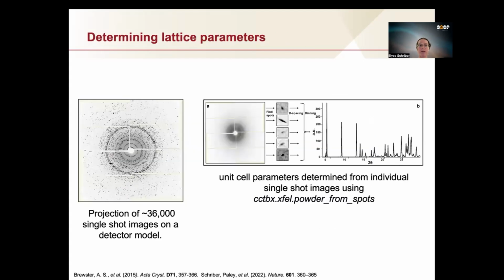So what we developed, using an already made algorithm that was used once previously in 2014 in development of new techniques, is we found that you could determine the lattice parameters from the XFEL experiment. As we said, thousands and thousands of these randomly oriented crystals are sampled, and we get these single shot images. If you take 36,000 of these single shot images and you project them onto a detector model, you start to see what looks almost like a 2D powder diffraction pattern.